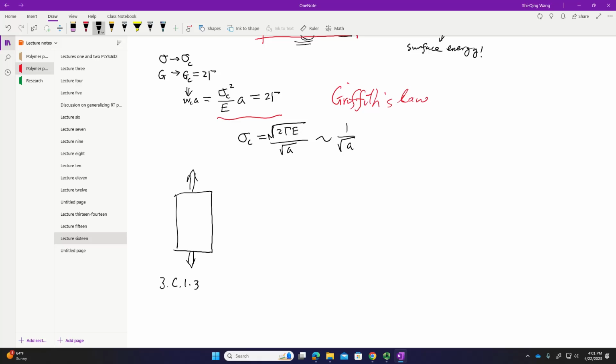In that limit, how do you characterize your material? One way is the nominal strength. What is the second variable? Young's modulus, which gives you a sense of stiffness. What is the third variable? Maybe the strain energy density, which in the boring linear elastic limit is nothing but sigma squared over E. In other words, you only have two variables: the nominal strength and Young's modulus, because the third one is given by the first two.